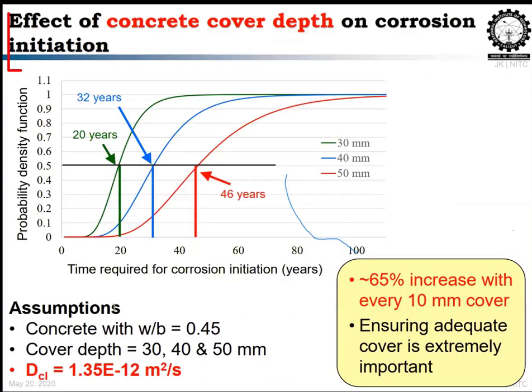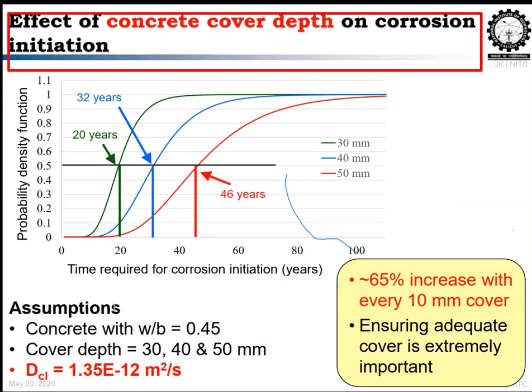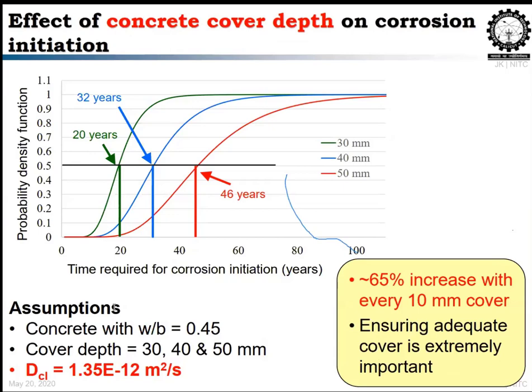And the importance of cover depth is a very important parameter that we usually miss on site, where we don't maintain the proper cover. In this graph, I have compared a situation using 30 mm cover, the green line, 40 mm cover, the blue line, and 50 mm cover, the red line. All the scenarios are the same, just varying the cover depth of a particular section.